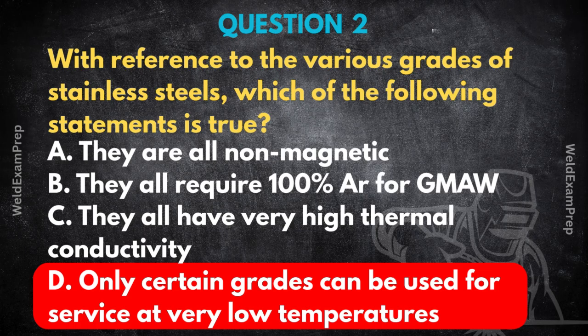Yeah. While the austenitic stainless steels, your common 304 and 316 grades, are typically non-magnetic because of their crystal structure, other types, like the ferritic and martensitic grades, think 430 or 410, are definitely magnetic. And even some austenitic grades can become slightly magnetic if they've been cold worked. So definitely not a universal rule. Good to know. What about B, the 100% argon for GMAW?